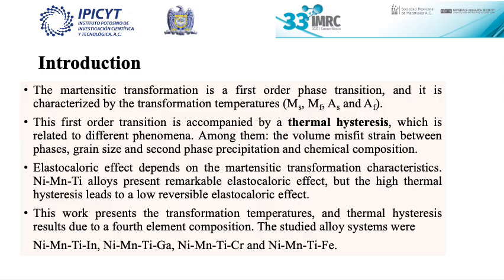Elastocaloric effect depends on the martensitic transformation characteristics. Nickel manganese titanium alloy presents remarkable elastocaloric effect, but the high thermal hysteresis leads to a low reversible elastocaloric effect. This work presents the transformation temperatures and thermal hysteresis results due to a fourth element addition. The studied alloy systems were with the addition of indium, gallium, chromium, and iron.